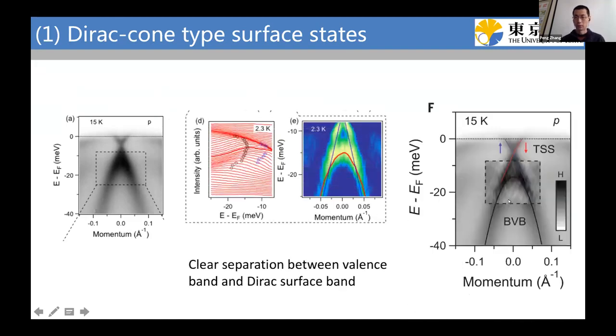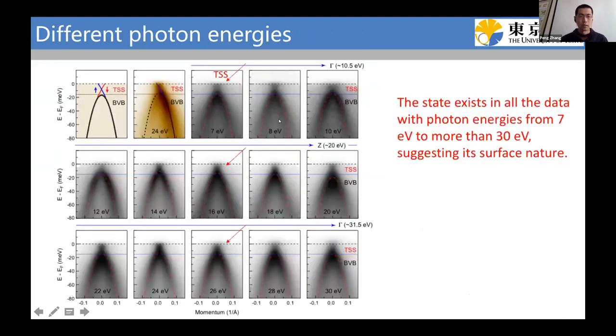So we summarize the band structure here. We have a bulk valence band, mainly from the dxz orbital, and on top of this band, we have a cone structure. We also measured the photon energy dependence of this state with a low energy synchrotron. The energy range is from 7 eV to more than 30 eV. But the energy resolution is much worse than our high energy resolution ARPES in the lab, so we cannot distinguish the details of this cone structure. But at least we see that this state exists for all the photon energies we measured. So this suggests the surface origin of this cone structure.